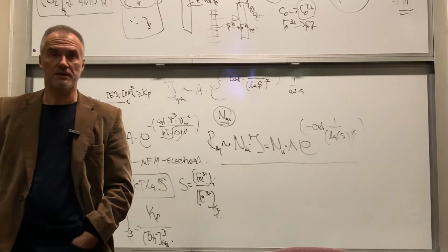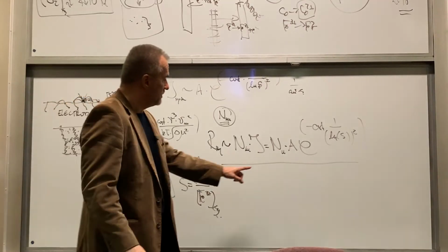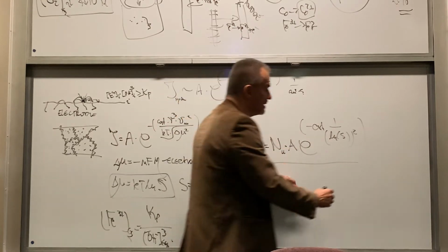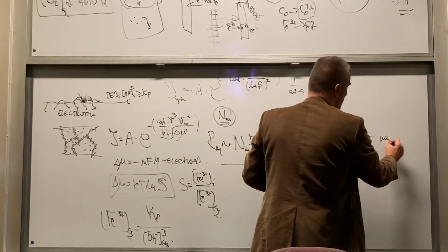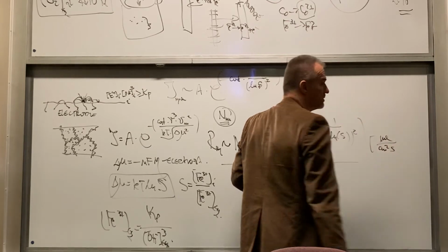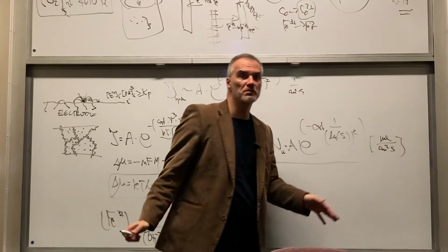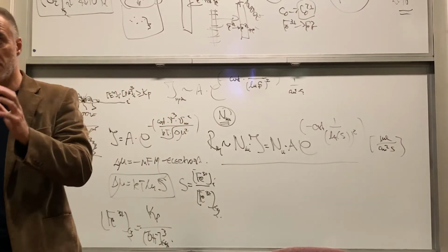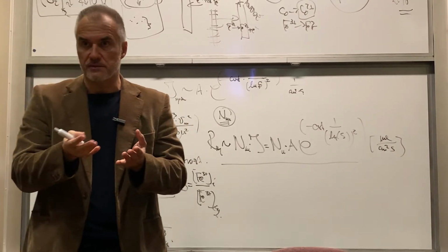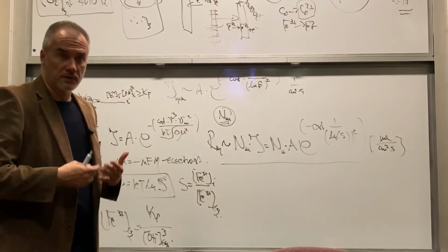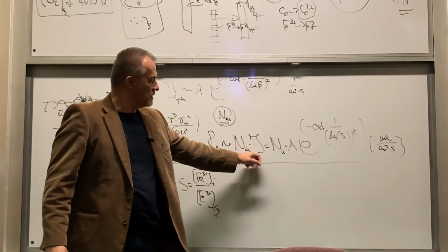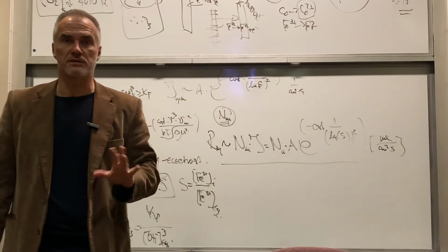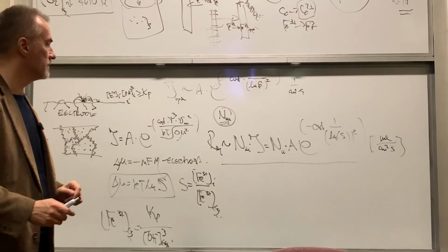That will be the rate, and if this is moles and the whole unit of this is 1 over centimeter squared second, it basically has the unit of flux, which is mole per centimeter squared second. So we are doing a little bit of a trick, assuming that every nucleus that is formed grows to a certain size and incorporates. And so for that reason, the incorporation rate is proportional to the nucleation rate times this average size of the hydroxide. That's the whole story.